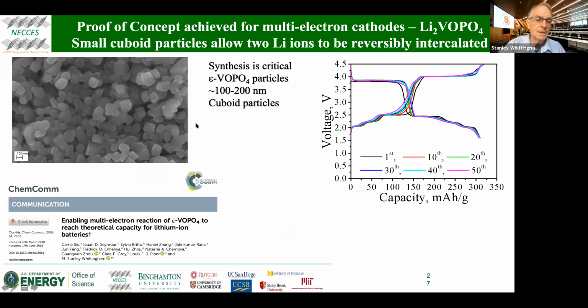And Kerry Sue, who was my lead student on this, who's now at Argonne National Lab, was able to synthesize these little cuboids. They're about 100 to 200 nanometers in size. Very uniform. A lot of our earlier synthesis gave us micron-sized particles. These were not very reactive. And when we used grinding to reduce their size, we in fact changed the coordination number of the lithium and the vanadium in there. And this was Clare Grey's work at Cambridge, who said, you're doing damage to the materials. That's why we went back and made these very pure materials.